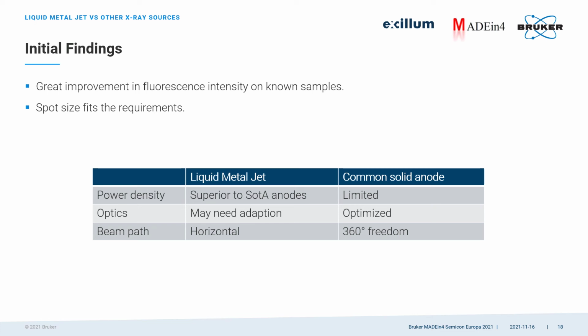Our tests have shown that the X-ray optic may need some modification for best results, because these optics are optimized for the common microfocus tubes. Also, the beam path for the MetalJet is horizontal, whereas the common solid-state microfocus tubes have the full degrees of freedom to mount the source.